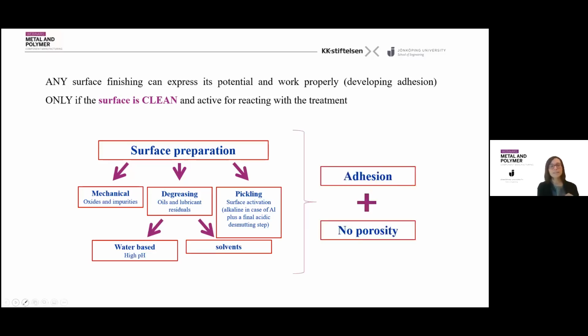This activity, this reaction and bond-forming with the coating, is what gives you the adhesion you need and avoids the formation of defects in the coating. So if you concentrate your effort on surface preparation, then you can achieve adhesion and no porosity in your surface treatment.